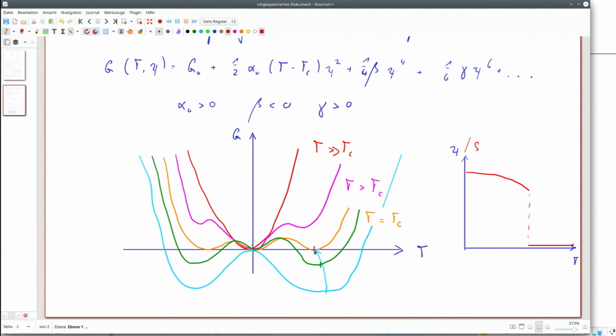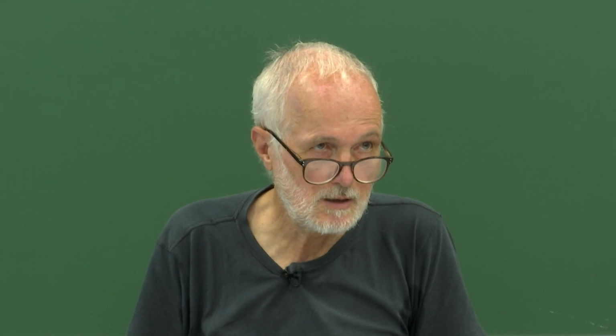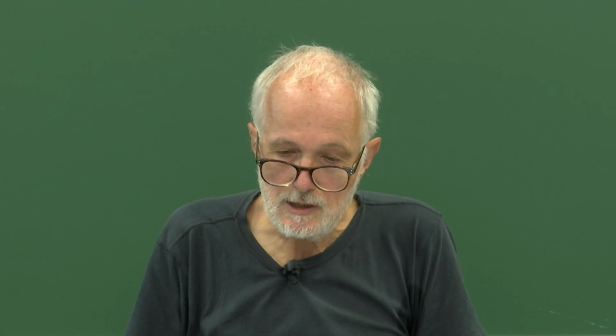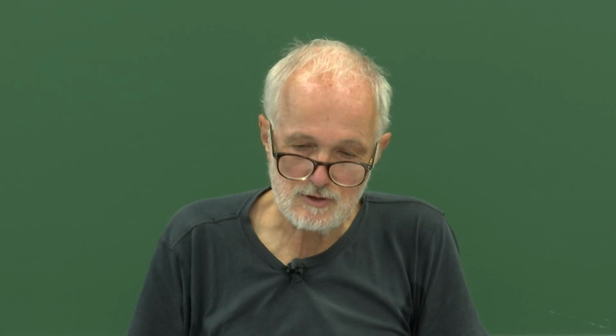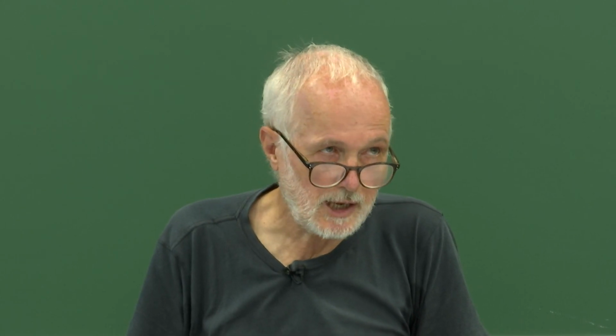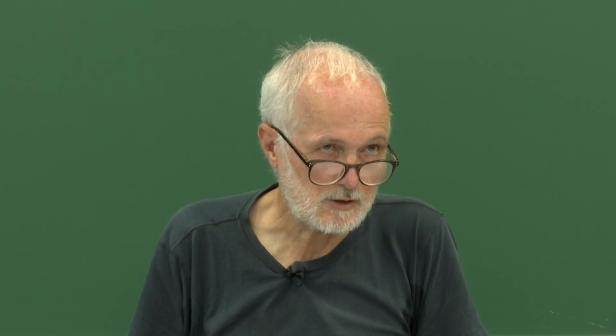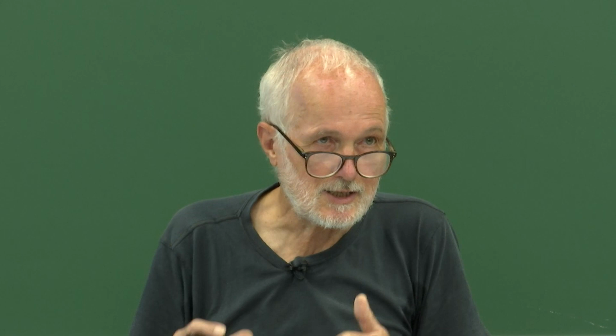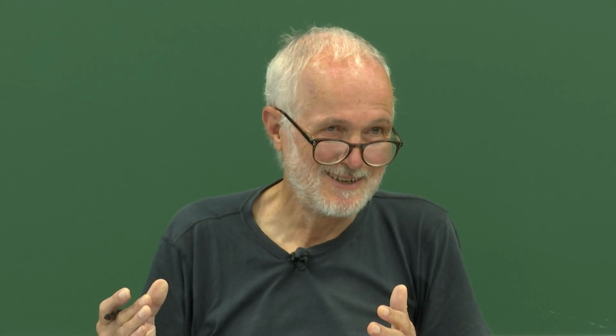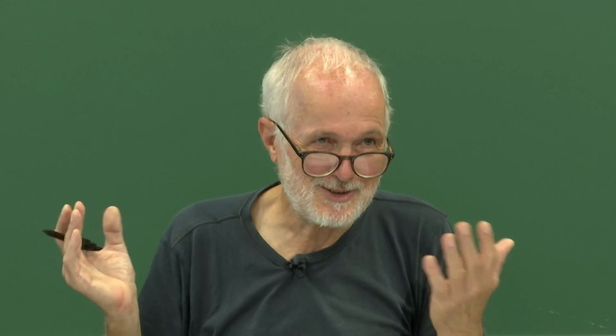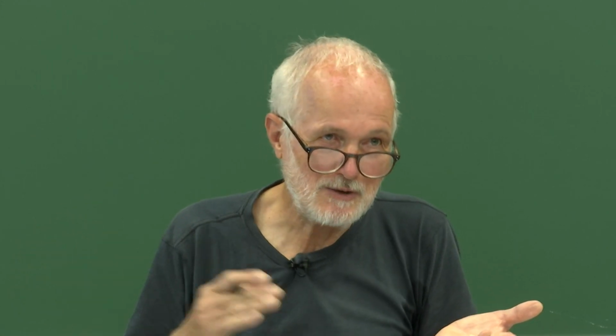So we have something we call metastability. The system would stay for some time in this disordered state, even if you're somewhat below the transition temperature, still there is a metastable minimum here. And only if you're here, this is the loss of stability, then the system would spontaneously do the phase transition. And that's something we always have to struggle with, if you are studying all kinds of phase transformations on a computer, that you have this metastability.